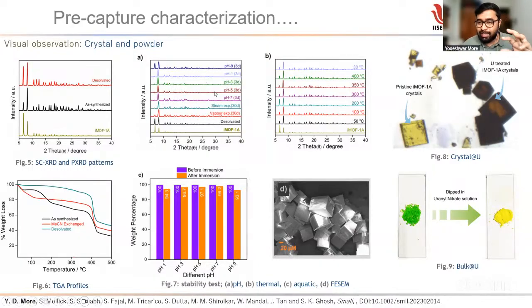So we analyzed that the MOF is quite stable in different pH ranges as well as it is temperature stable. That can be seen here from the TGA. You can see the TGA of the activated phase is stable up to 400 degrees centigrade. It means the MOF is quite thermally stable. But suppose we have taken a bulk of MOF crystals, and suppose it has 1,000 crystals, if even 800 crystals give the stability, the TGA profile will be flat. Then how to identify it?